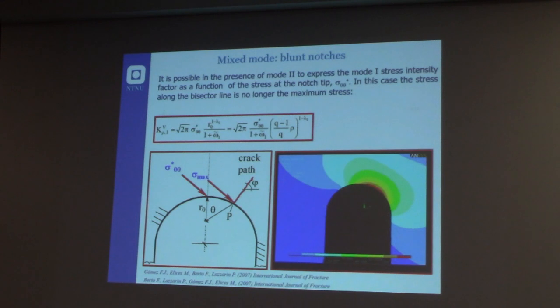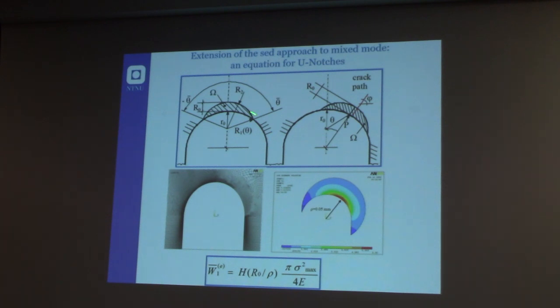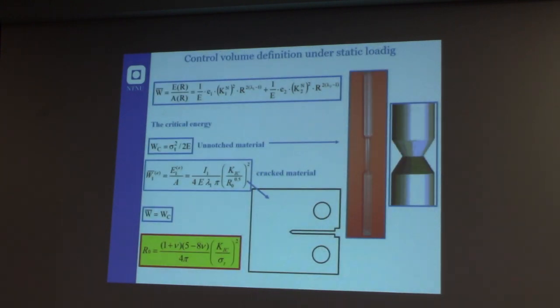So we apply the same concept to mixed mode loading. We consider the maximum tangential stress approach, so a kind of local mode 1 approach. We consider that along this bisector line we have mainly mode 1 loading. So what we did was simply rotate the volume under pure mode 1 to a volume like this, maintaining the length R0 for both volumes. It is simply a rotation of the volume. So the method can be applied also to mixed mode conditions. And we define the control volume radius R0 as a function.